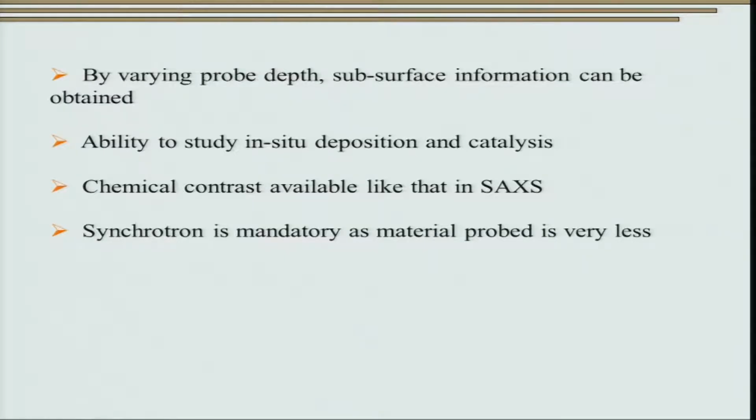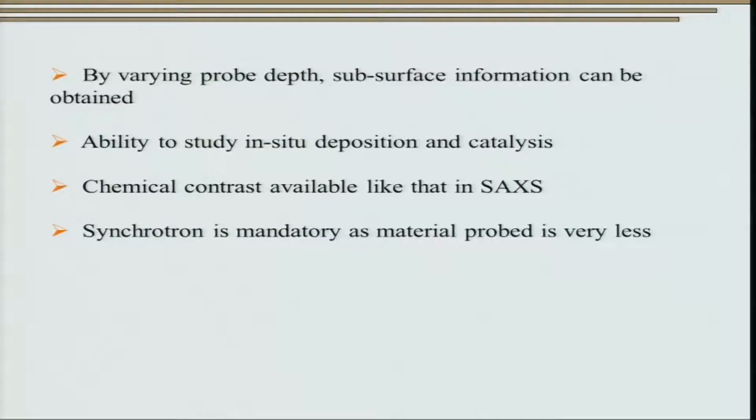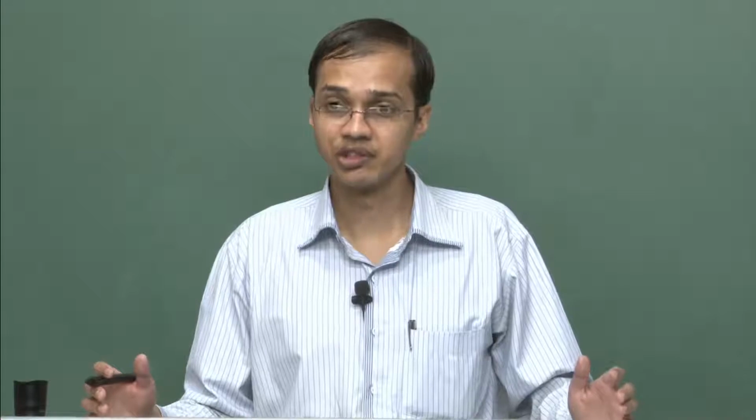The best part about GISAXS is that simply by varying the probe depth, the depth to which the X-rays are penetrating, we can study subsurface information. We can obtain significantly important subsurface information using GISAXS. This is particularly important for studying subsurface damage caused during, say, something like implantation. The other important aspect which is very important,